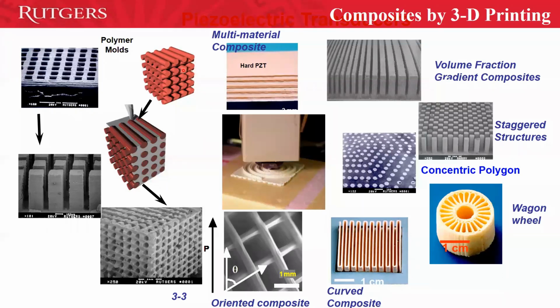With 3D printing, we made molds, and from these molds we made really fine scale composites. This is a plastic, reusable mold to make a 1-3 composite, or a volume fraction gradient composite, concentrating the major property in the center and going lower in property toward the side of the composite. Specially, we have a patent on this one, the wagon wheel composites, and this is another outstanding composite made by 3D printing.